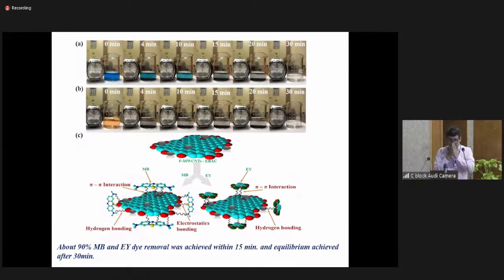So this shows that in only around 15 minutes we can remove 90% of the methylene blue and Eosin Y dye. 15 minutes. Earlier we were taking 5 hours, then it reduced to 1 hour, then to 30 minutes for equilibrium. So we can remove the dye in only 15 minutes by using this functionalized carbon nanotube incorporated activated carbon, which is formed from the eucalyptus bark.